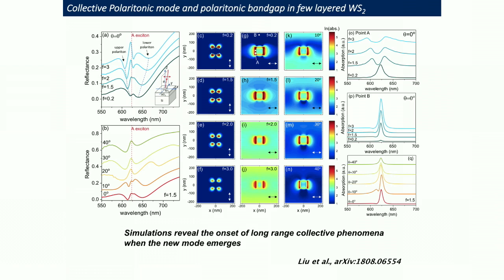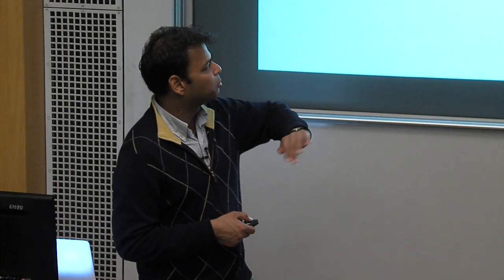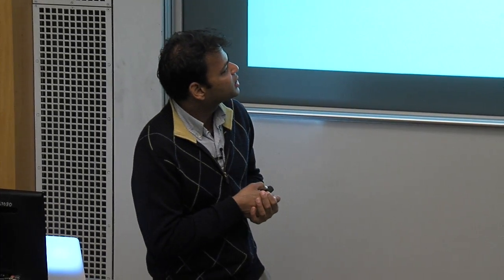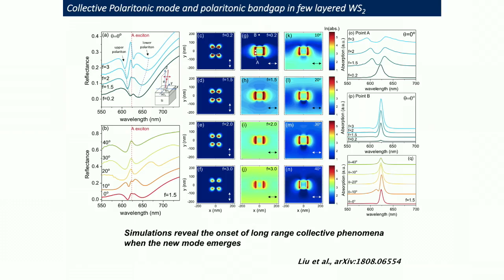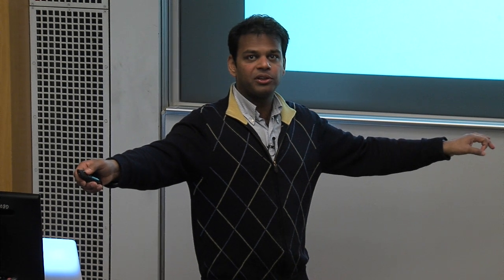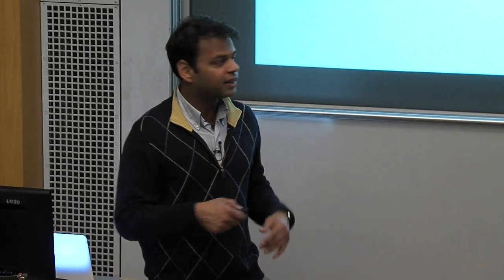But as we start to increase the number of excitons in the system, going from monolayer to bilayer to trilayer or beyond, we started to see something very interesting. When we increase the number of excitons, the exciton that is initially far away now starts to see the field of this plasmonic particle, which is otherwise very far from the interaction regime of this local plasmonic field. So this was telling us that as we increase the oscillator strength, or the number of excitons in the system, it becomes collective, in the sense that excitons in physically separated regions in space start to interact with each other via this plasmonic field. And this is the reason why we have this new mode.